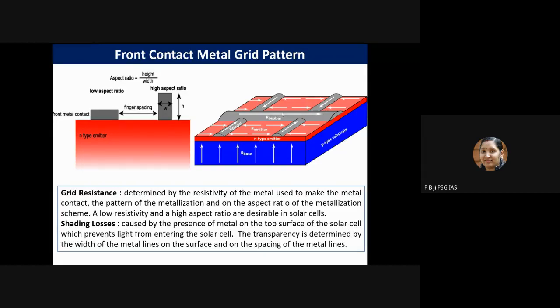Now if you see the front contact metal grid as a schematic diagram I have shown here, there are some parameters which are very important. One is finger spacing, this inter-finger spacing. That is something we can play around with, or optimize, in order to improve the efficiency of a solar cell. And the second parameter is the aspect ratio of these fingers. Aspect ratio is nothing but the ratio between height and width of these finger lines. If you can increase the aspect ratio of the finger lines, that is an advantage towards increasing the performance of the solar cell.